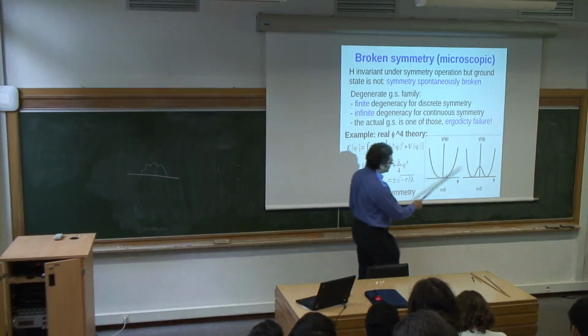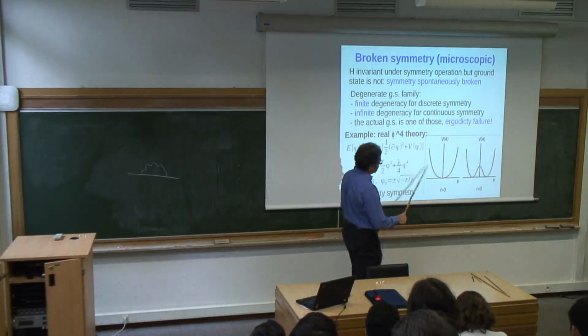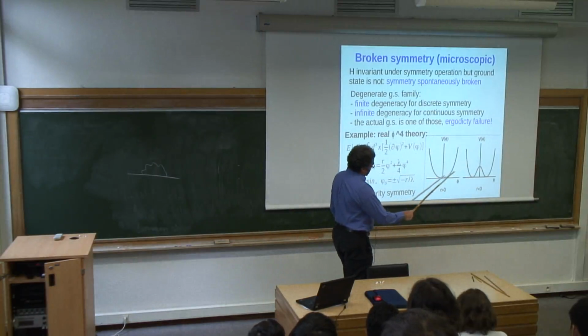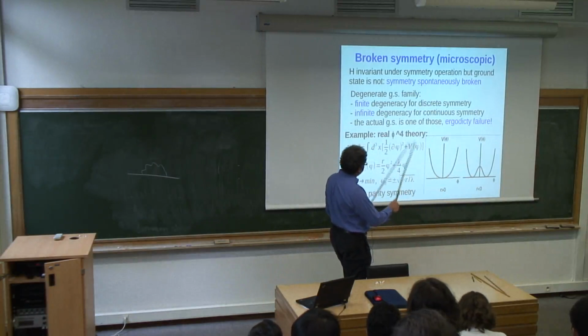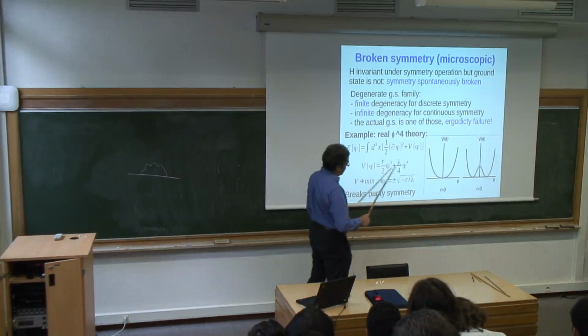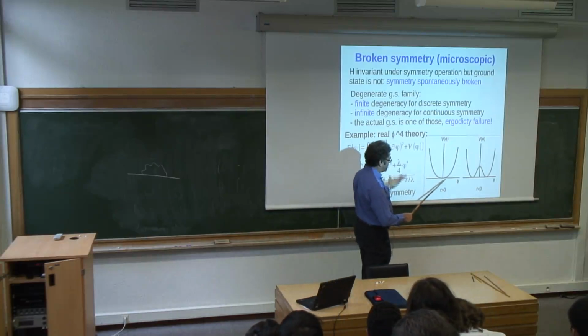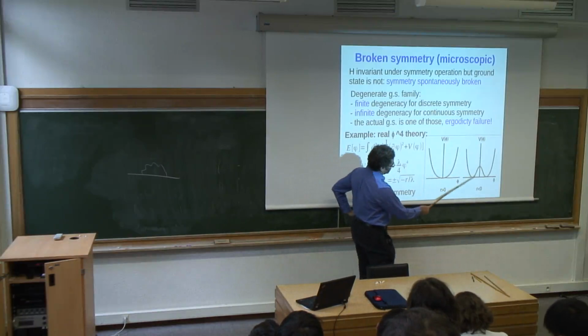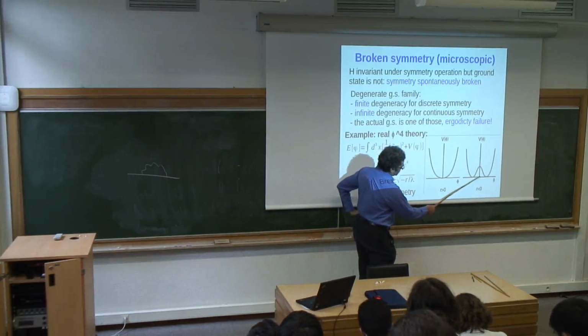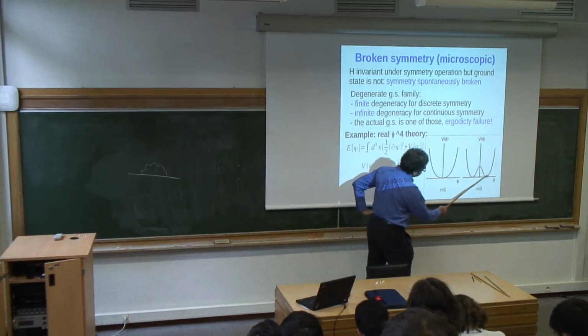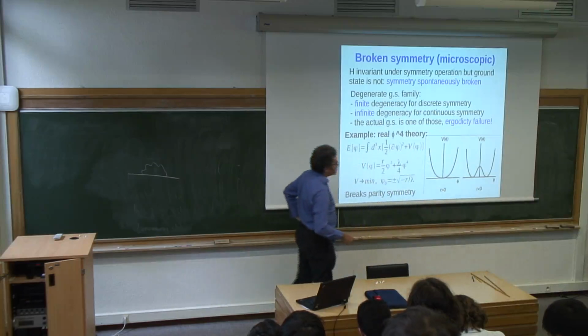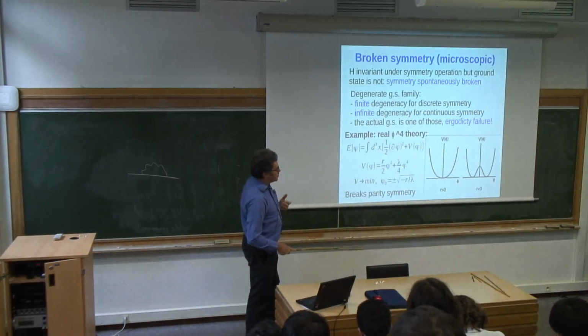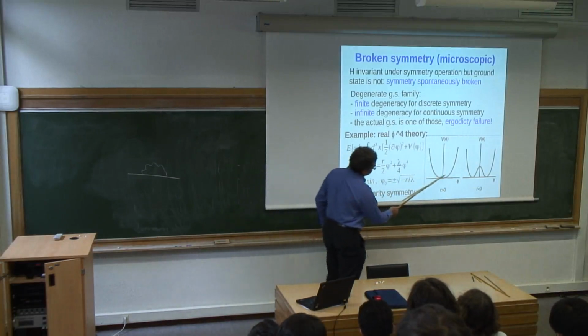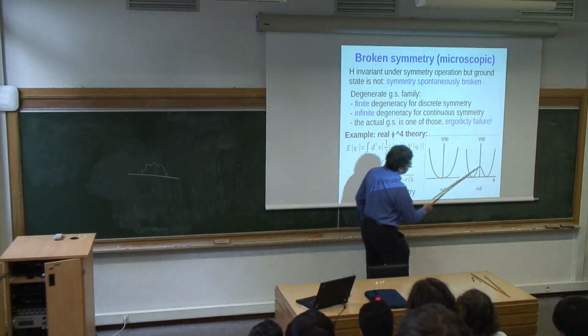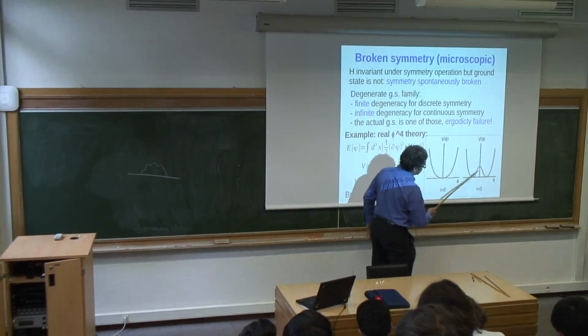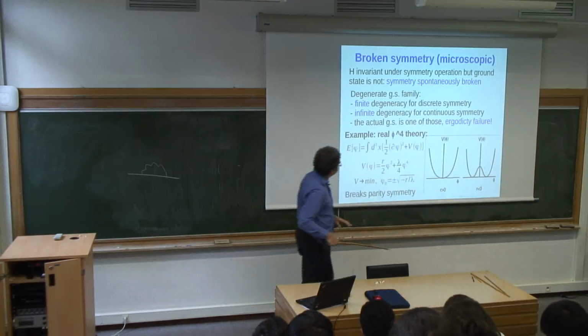And the classic example of that is this phi-4 theory with the effective Hamiltonian that has positive curvature at temperature above the transition, negative curvature at temperature below the transition at phi equals 0, and then it develops two minima which are equivalent but distinct. And so the system, if it was here at temperature above the transition, will go here or here below the transition, so it will be two different states.